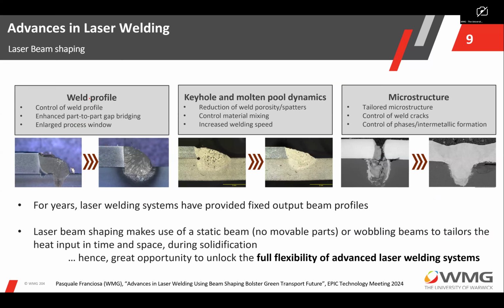Probably for three reasons. First, because we can have a more optimized weld profile, or we can control the weld profile. Second, and this is probably where most people are focusing their effort these days, is the control of the molten pool and the keyhole dynamics, eventually for reducing porosity and spatters. And then another area which we see of interest is the control of the microstructure. Now, statistically speaking, there is a lot of academic work and industrial implementation in the first two areas, so weld profile and molten pool dynamics. There is very little on using beam shaping for controlling the microstructures.